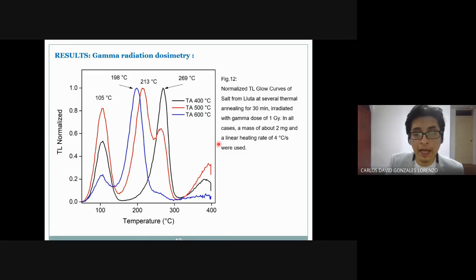It appeared that with increasing thermal annealing, this maximum TL intensity, this prominent TL peak, shifts to the left. So for this reason, I studied this behavior in more detail.